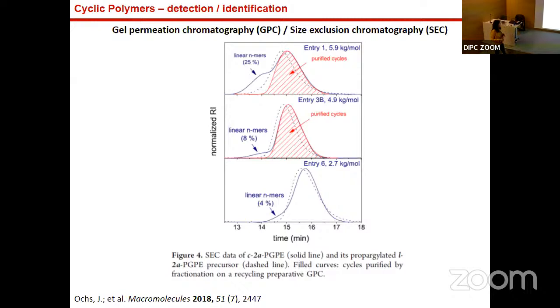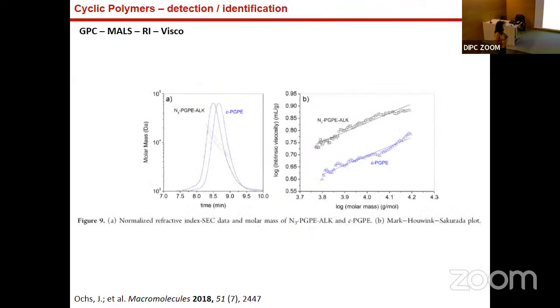Of course, we have to purify these samples. We did preparative GPC here, where we can separate this from this, and this is the result, the purified cycle. So this is very nice. And then we can measure the sample's specific physical properties without the linear impurities.